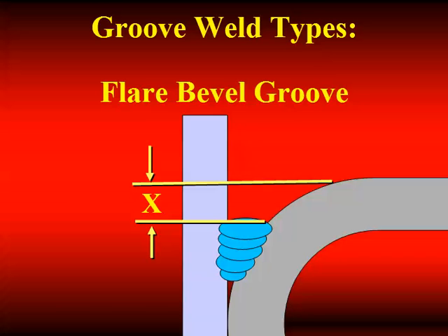Yes, sir. There was a big debate in the committees as to whether or not we should be measuring this face width or measuring this depth. And we ended up with measuring depth. So the way I see it is somebody's going to be putting a straight edge on here and using a depth indicator or some kind of gauge to find out what that is. And you're looking for a minimum amount of fill. So I would be looking at some kind of gauge to make sure I filled that adequately. So it's not so much a precise dimension I need to make. I need to just make sure I have the root totally filled. I mean, filled to that minimum point.